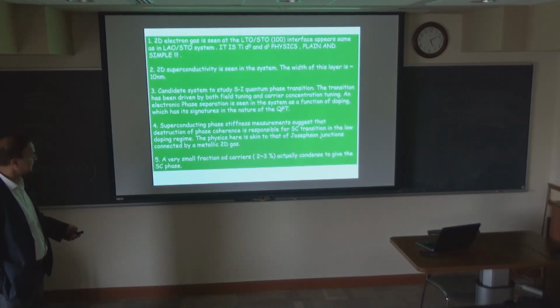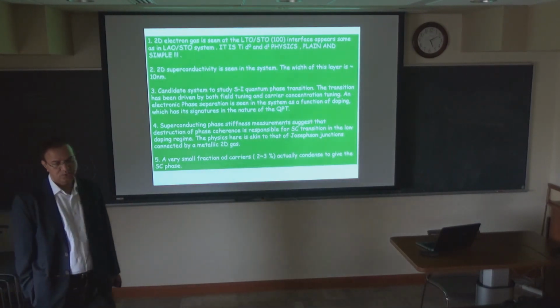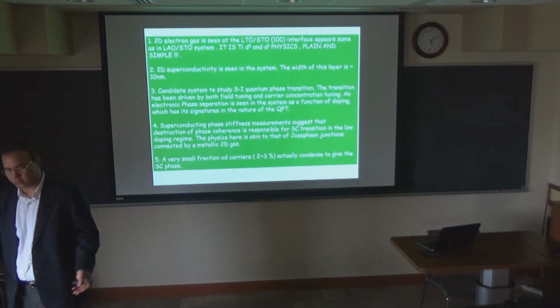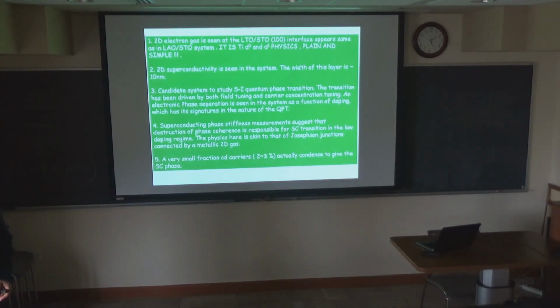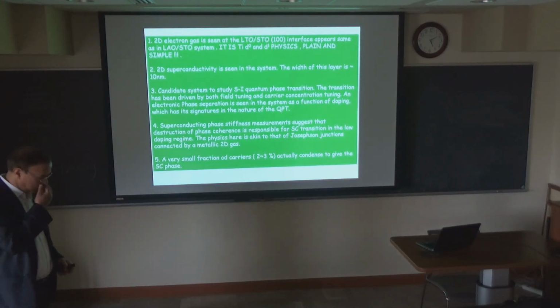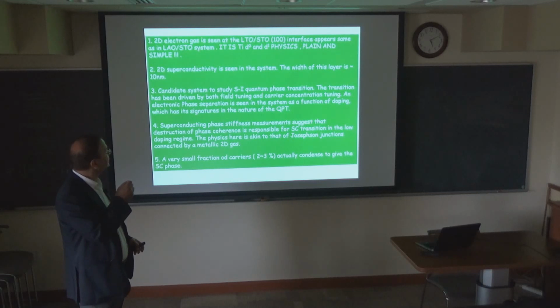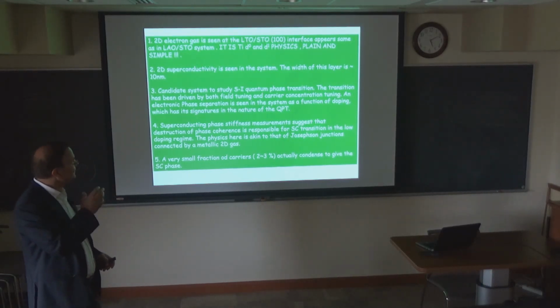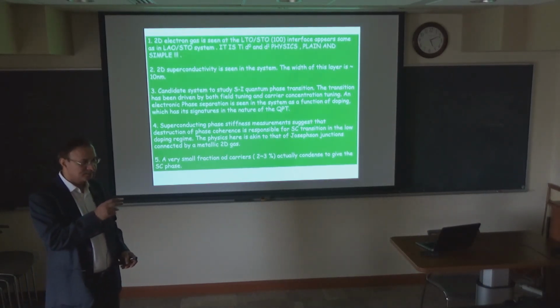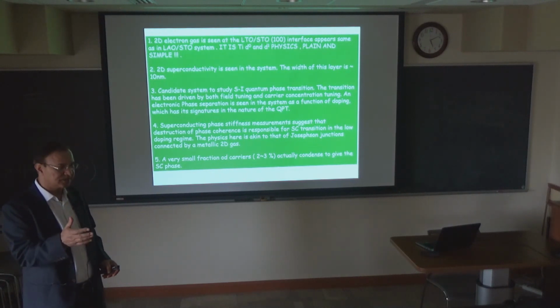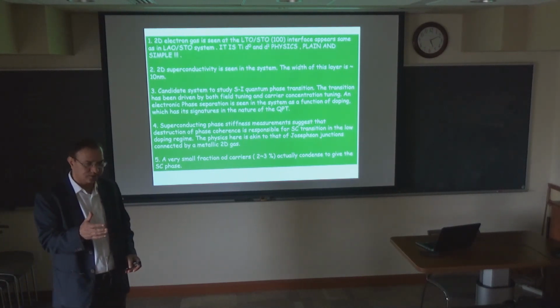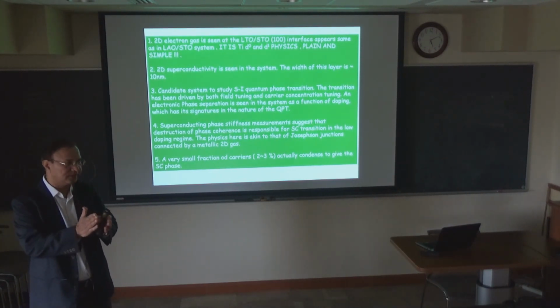Finally, a very small fraction of carriers, 2 to 3%, actually condense to give the superconducting phase. So this is the conclusion of all these experiments. And I don't know what we are going to do next. We want to look at this anisotropy a little more, but this experiment has to be designed in a proper way, because you cannot use very large samples. It has to be a very thin channel.